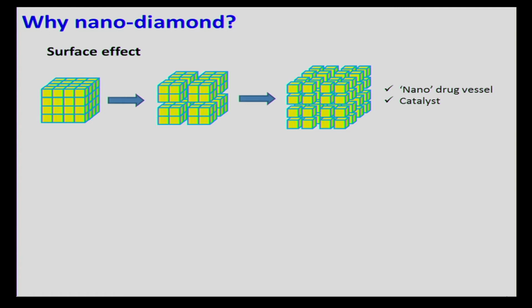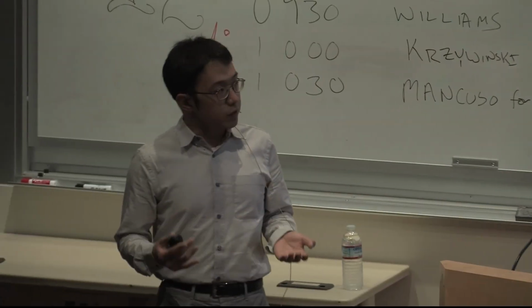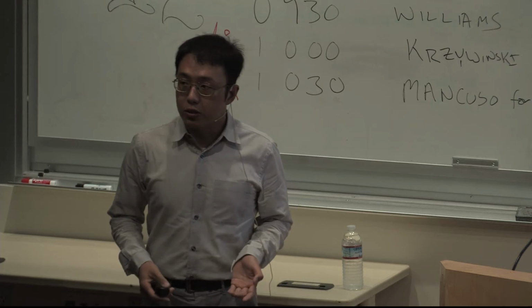There are two major effects that we are interested in. One is the surface effect. That is, if you have a bulk material and you cut it up, the smaller the particles you cut it into, the more surface you expose. And more surface means that you can, for example, carry more drugs per each particle, or you can expose more active sites to catalyze certain chemical reactions.